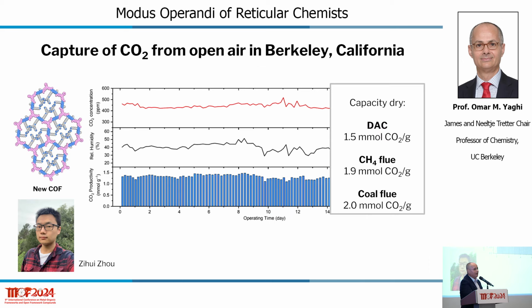This is the result. Okay, I'm showing you the result here of taking Berkeley air and pushing it through a powder of this COF. And here you see the CO2 level at the top in Berkeley. You see the humidity in Berkeley below that. And then you see in the blue bars the CO2 uptake. And it varies not because the material is unstable, but because the uptake is proportional to how much water is in the air. And if you compare the result at the same humidity, it does not change. In this case, over 100 cycles, and we continue to cycle this material. The uptake of this material is 1.5 millimole of CO2 per gram.